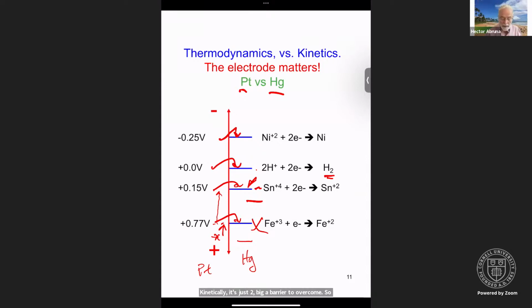So then you keep going, and you get to nickel 2 going to nickel 0. So now your mercury surface is coated with a nickel film. Nickel is better than mercury for hydrogen evolution, so you might start evolving a little bit of hydrogen here because it's easier on nickel than it is on mercury. So clearly, the electrode has an enormous role to play here. It is not just simply a source or sink of electrons.